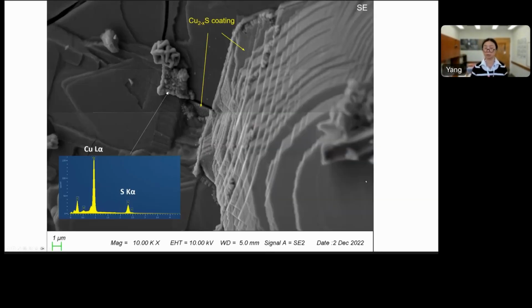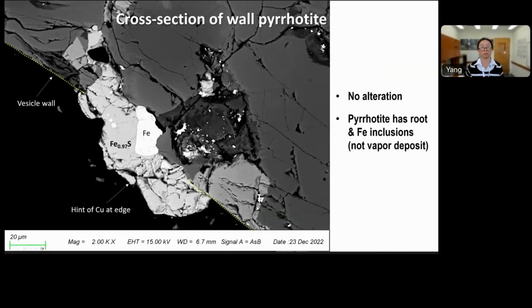This is another example. Including this example is mainly to show the EDS chemistry of the copper sulfide coating. So it's pretty pure. We don't see nickel or cobalt or even iron associated with those copper sulfide coatings. In order to check what happened with the iron sulfide grain, we searched for a cross-section of iron sulfide on the vesicle wall in the 2D section.